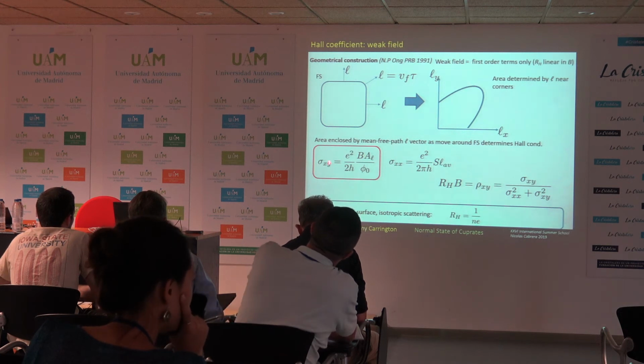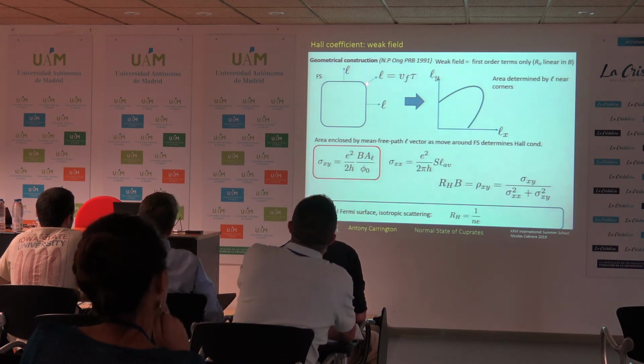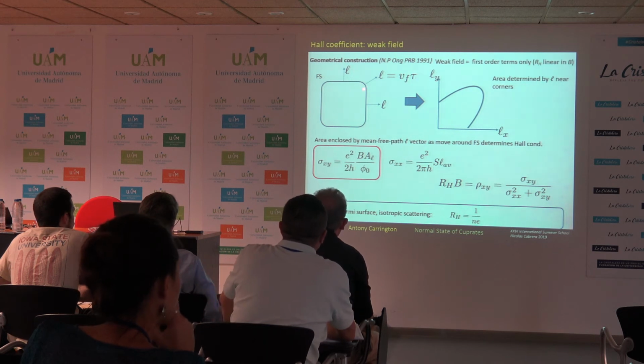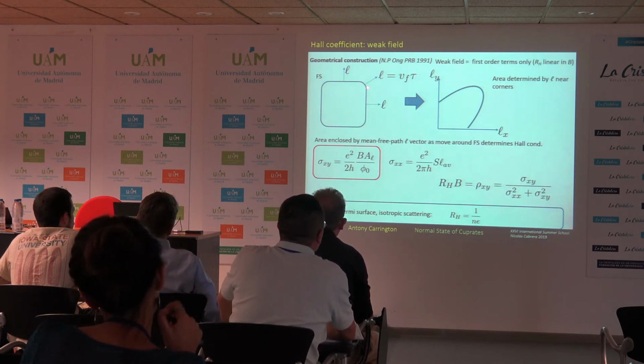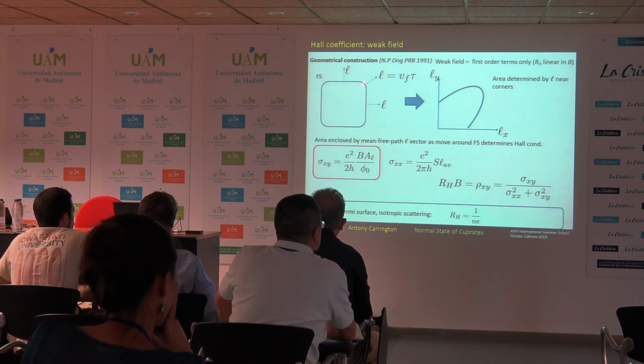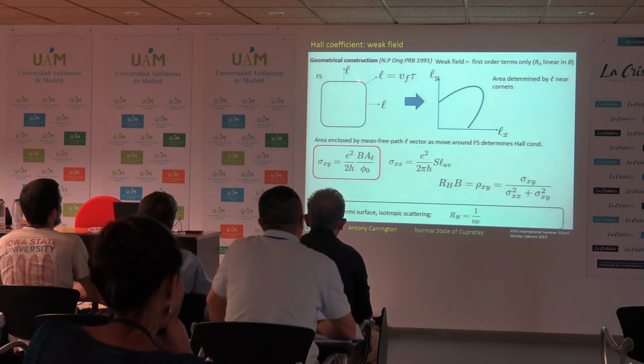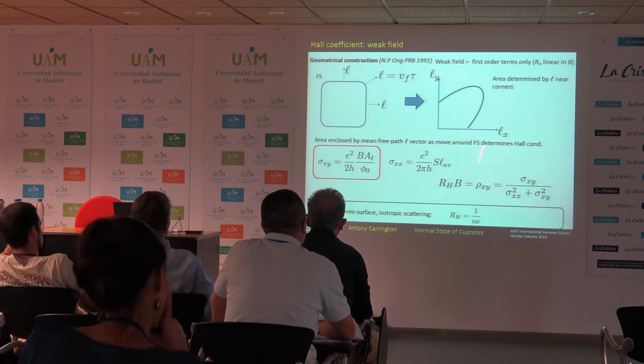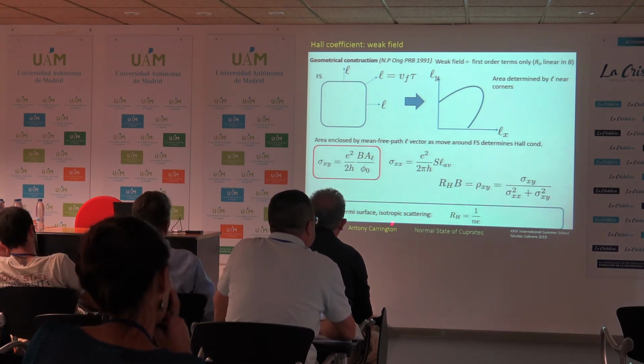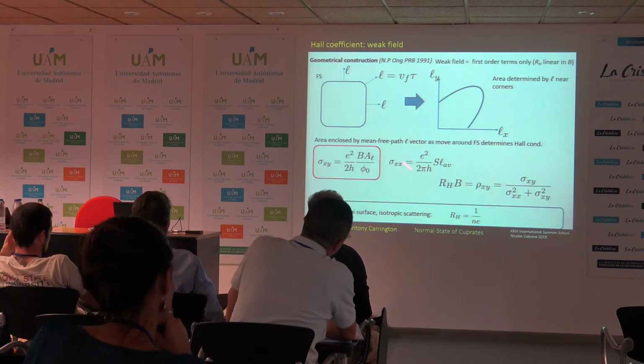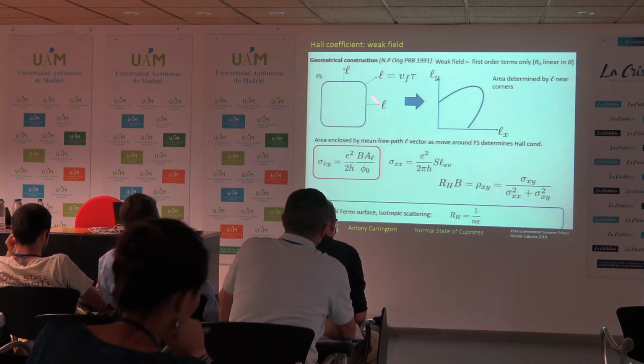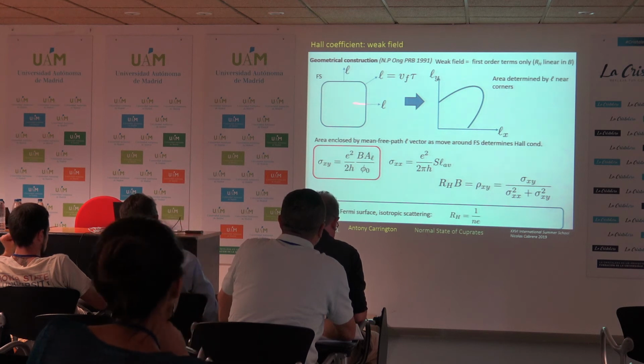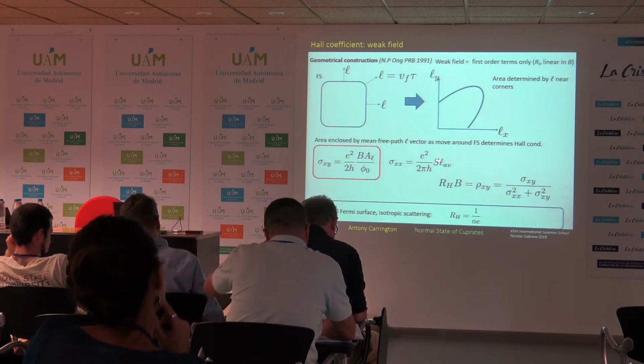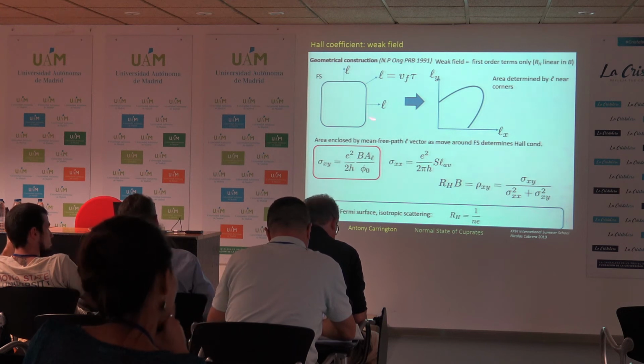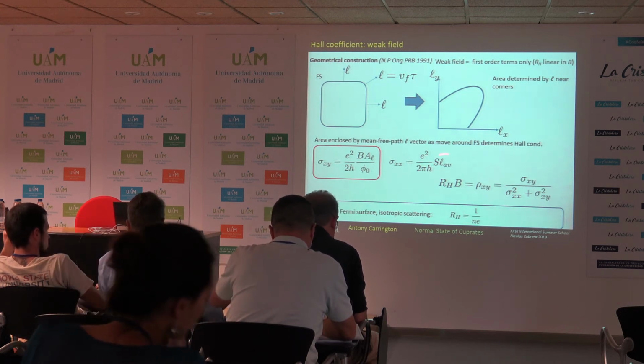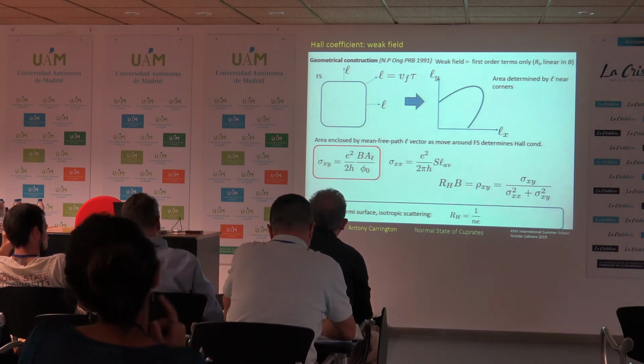And what you can see then is that sigma xy is dominated by what happens round about these corner regions. So what happens here is kind of fairly irrelevant. It's what happens here that matters. That's the thing that's going to determine this area. On the other hand, the longitudinal resistivity, sigma xx, just depends on pretty much a straight average of L around the Fermi surface. So it's essentially just S, which is the length around the Fermi surface, times some average of the mean free path.